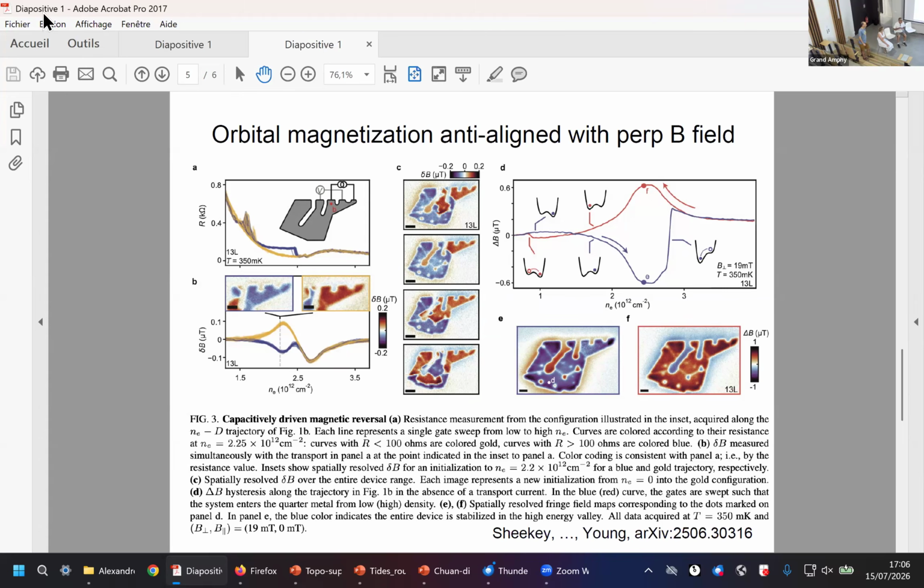Problems that I do not know. They don't make ABC. So you find them somewhere in your graphite, and it's a metastable region, right? If you anneal it, it becomes Bernal. It's very long metastable, because it requires shifting the entire layer. You can find it. It's metastable, but it's not stable.